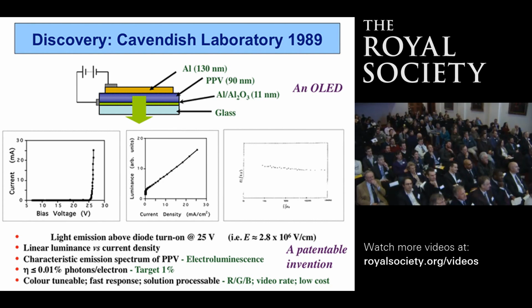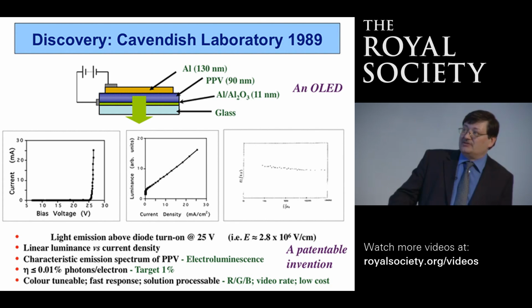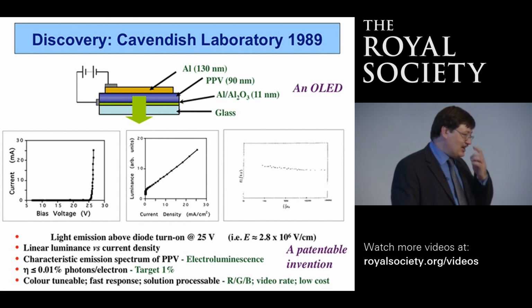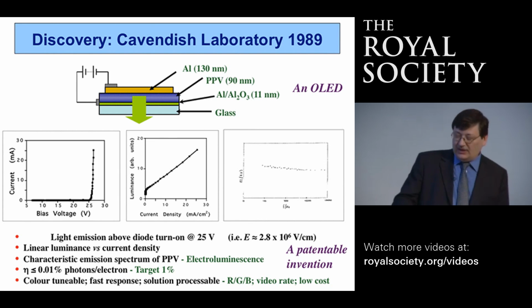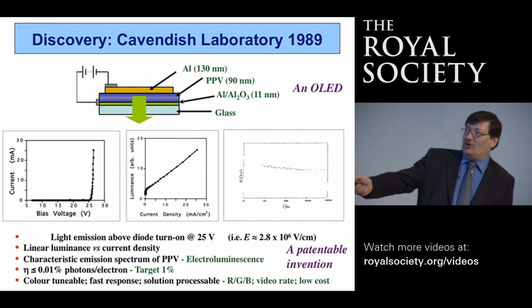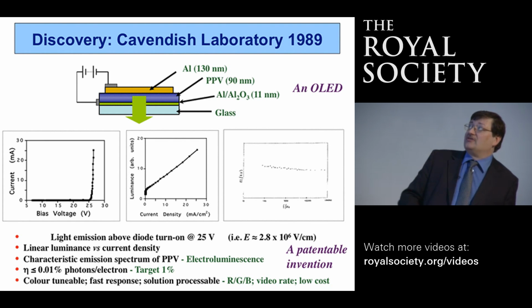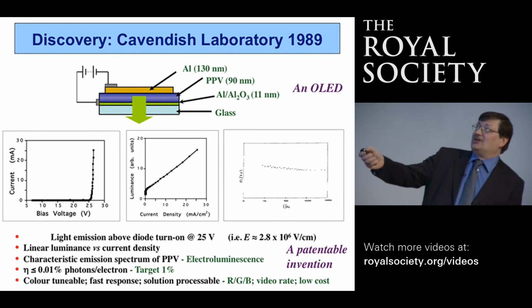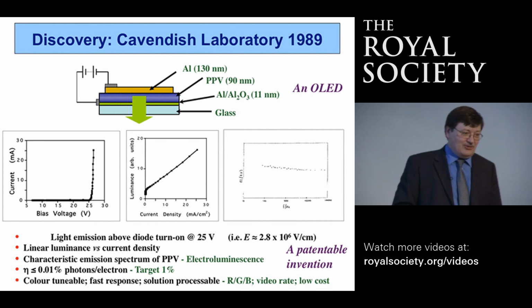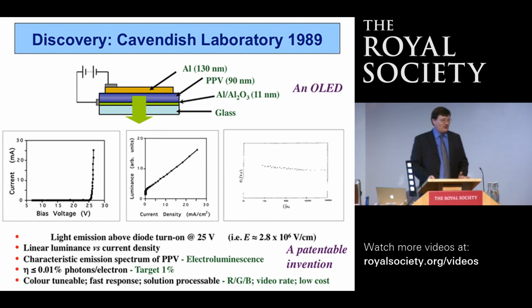And if you apply a bias to this structure, this is some of the original data, basically you increase the voltage, you get to 25 volts, and then suddenly you start to see a current flowing through that device. And it's not a breakdown. It's actually, there is an injection of charge into the structure at that point, and you get correspondingly some luminance coming out of the device, not very much luminance, but there is some light emission coming out of that structure. And so this structure is actually an organic light-emitting diode. It wasn't designed to be, and is certainly not the best device structure to achieve that.